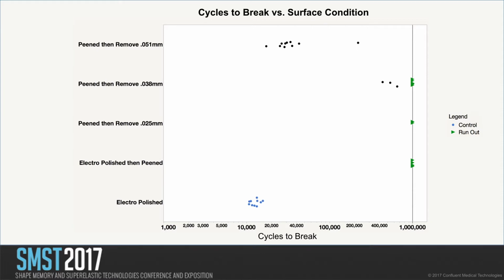We only have 3 wires present here due to the fact that we determined that wire state was not biocompatible, so we move on to our next wire state, which is peening and then removing 0.038 millimeters of material. Here we see a couple of fatigue breaks starting around 400,000, but of the 12 wires, we still had 9 meet our runout criteria, which is a massive increase from the purely electropolished wire.